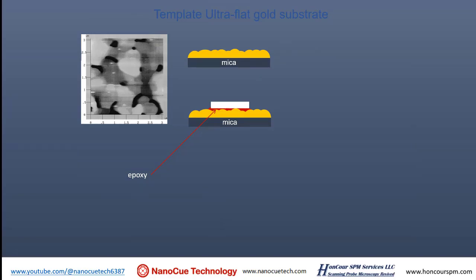And before you use it, you bend that mica, you strip a piece out. Okay. Now you expose the gold surface that is flat and that's clean. And this works very well because you can make 50 pieces of sample and then use it as you want. And the gold is clean and it is very flat. So you use the flat part.